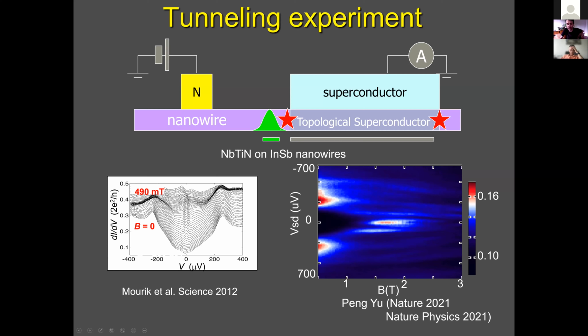Now let's talk a little bit about these data, how they're measured. So you set up this device, you measure current here, and what you plot is dI/dV, so conductance or differential conductance, which can have a peak at 0 voltage. So at 0 magnetic field, we are missing one ingredient. Remember, we need Zeeman splitting. So what we have is this kind of spectrum with 2 peaks at finite bias and a suppression in the middle. So this is just a manifestation of the induced superconducting gap, where some states are expelled from the middle and piled up on the sides. So these kind of features are well known. BCS peaks, they're called. They're superconducting quasi-particle peaks.